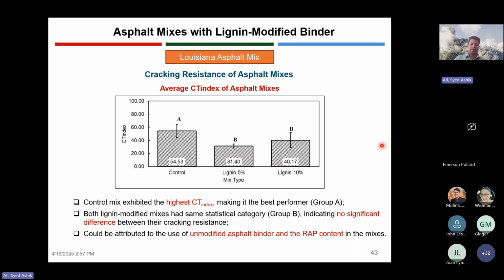So we asked ourselves what actually happened that the CT index value went down. One factor was that we used a pretty high amount of RAP along with lignin, 20% RAP with lignin, which could have been a problem. And also, we used an unmodified binder. If we had used a modified binder, some amount of SBS modification, that could have helped.